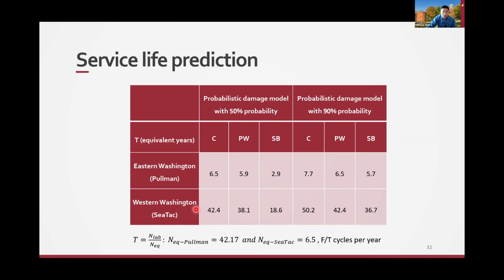Another consideration is that we consider the worst case, which means whenever the surface freezes. But we know for concrete, depending on how thick it is, it takes time for the frost to penetrate the concrete, right? So if the concrete or shotcrete is thicker, the number of freeze-thaw cycles will be lower, which means the service life will be a little bit longer than what you have seen here. This is the worst case we are using as an estimate.